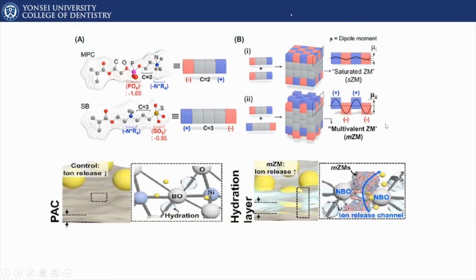This multivalent zwitterionic material is very interesting because it causes a disturbance of bridging oxygen and non-bridging oxygen of the glass particles. So because of this phenomenon, the glass particles from the glass ionomers are having a formation of ion release channels. And this will allow ions to be released from these glass particles to the outside very easily.